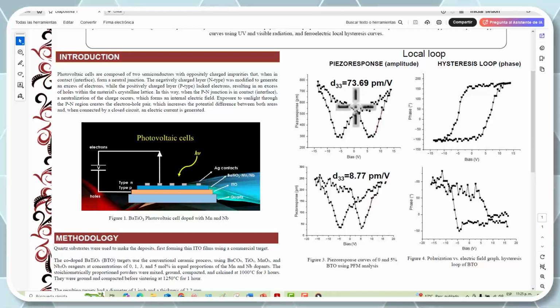The slope of these curves allows the piezoelectric coefficient D33 to be determined, which indicates the deformation of the material upon application of an external voltage. The D33 coefficients decreased with the introduction of the dopants, reaching a minimum value of 8.77 pm/V in the 5% sample.